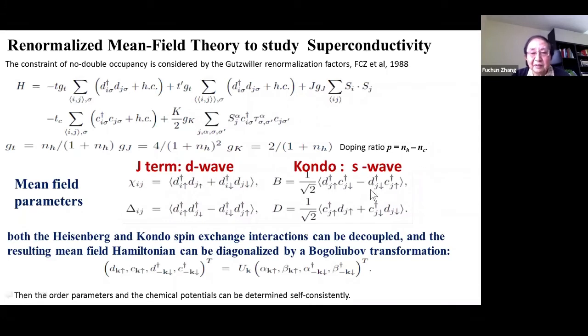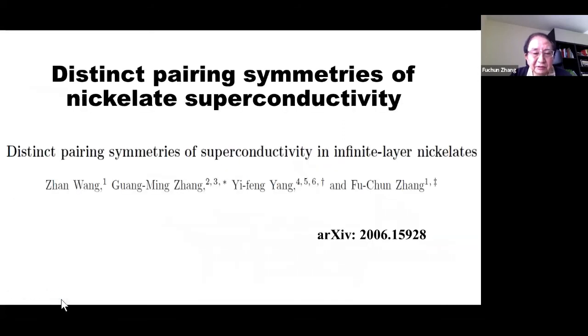And it's important to note, before we do the calculation, that the J term from the spin-spin coupling favors a d-wave, which we learned from cuprates, because you want the chi to be isotropic along x and y. So this pairing should be d-wave, right?